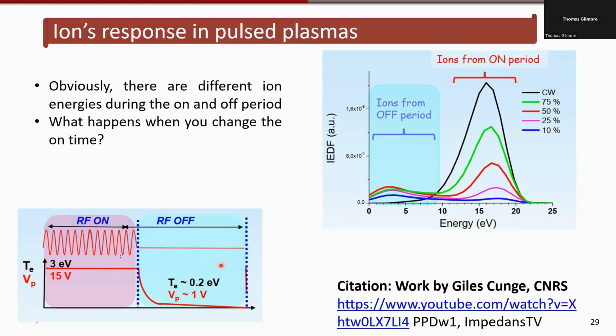When you look at the ion energy distribution function in this case, you basically see the distribution function for when the RF is on and when the RF is off. So here's the case where it's on, so you have some amount of power, and then in the off period, you see ions from the afterglow. The plasma potential is dropping rapidly, so you get very low energy ions. Okay, so this is typical. You get these different levels.